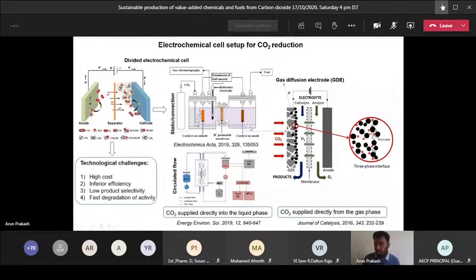But the thing you have to look into is that you are using a 100 micrometer electrode, but the catalyst is 10 micrometer, and the reaction happening will be in the nanometer regime. So we have to consider all these things when designing your system. The gas stream and electrolyte stream can be separated using a membrane, and using a divided cell can help overcome the pH limitation. So the other reason for using the divided cell is that it can overcome the pH limitation, and it can also promote CO2 transport and industrial current density.